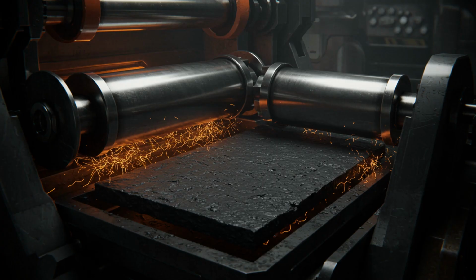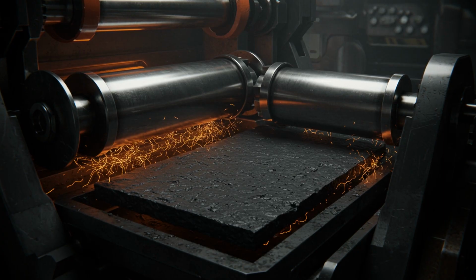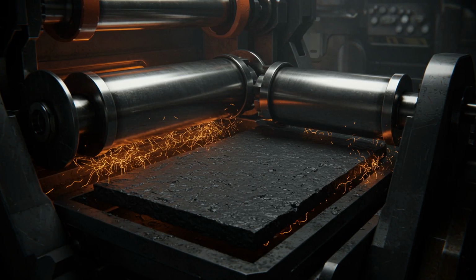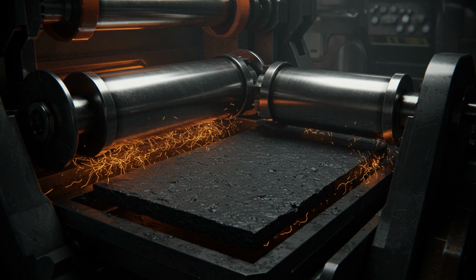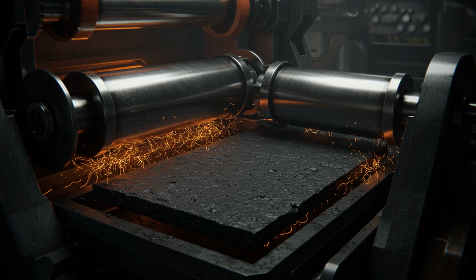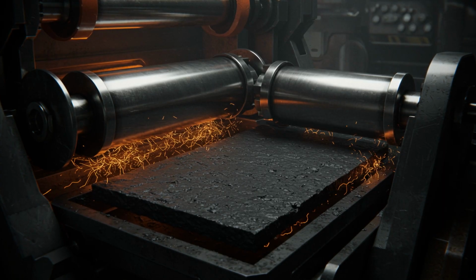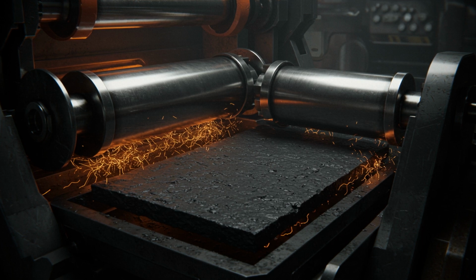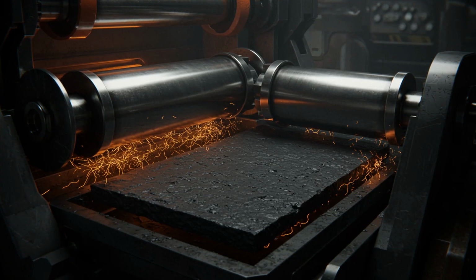To maximize energy density, we must remove every microscopic pocket of air. This is the calendaring process. The coated foils are fed between two massive heated steel rollers. These rollers exert a staggering pressure, often exceeding 100 megapascals. That is like imagining the weight of a professional locomotive concentrated onto the tip of a finger. This pressure crushes the slurry particles together, increasing the material's density and improving electrical conductivity. As the sheet passes through, it becomes thinner, glossier, and much tougher.